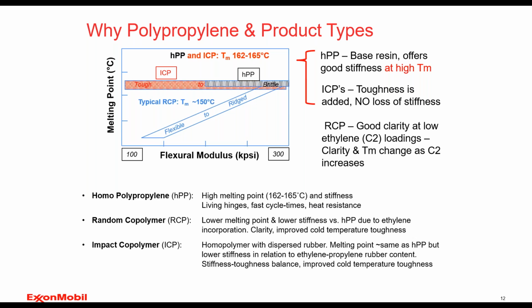So in contrary to that, the random copolymer, where the ethylene is inserted at random intervals throughout the polymer chain in more or less a solution stage, that can offer benefits of improving the ductility of the random copolymer. At a very low level, say below 4%, you can still maintain some good clarity of random copolymers. But if you add too much ethylene modifier, you end up losing that flexibility. The RCP goes from being very rigid to very flexible, and certainly the haze aspects, it gets hazier and hazier with the amount of ethylene added. Ethylene is referred to as C2 here.